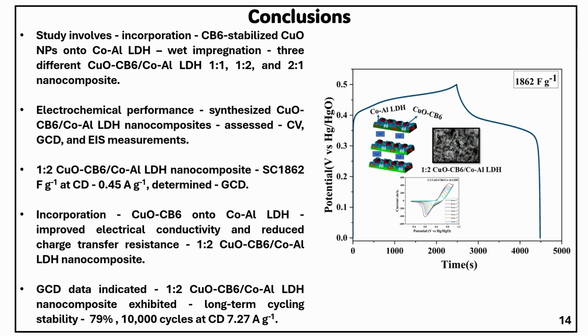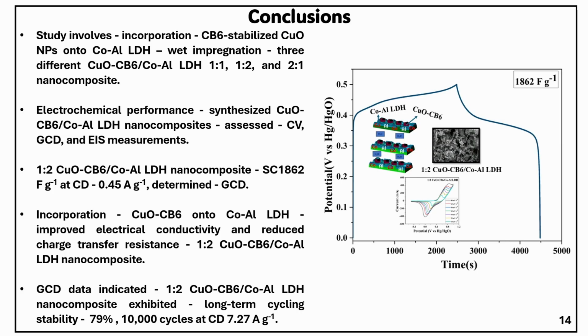The incorporation of CuO-CB6 onto the cobalt aluminum LDH layer decreased the resistance and improved the electrical conductivity, as shown through EIS analysis. Additionally, GCD data indicated that the 1:2 nanocomposite exhibited a long-term cycling stability of 79% even after 10,000 cycles at a current density of 7.27 ampere per gram. Thus, the synthesized 1:2 nanocomposite can serve as a promising electrode material for supercapacitor performance.